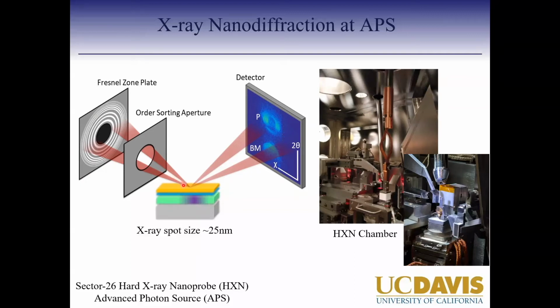Because you have X-rays at 10 keV, they can penetrate as many capping layers as you have. Remember, this material has gadolinium and gold. So electron penetration depths are challenging, but X-ray penetration depths are totally fine for looking at this film, which is buried in these capping layers. Okay, this is the image of the chamber inside, and this is where the sample is mounted. The X-rays come in from here, and then you have the detector on this side, right here.